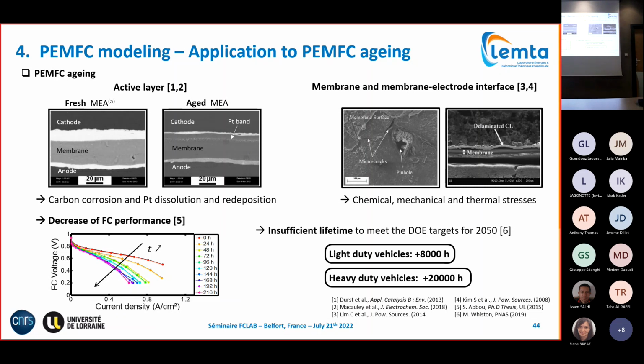Aging of fuel cell components primarily concerns the aging of your electrodes, more precisely cathodes, and to a lower extent the anodes, through carbon corrosion and platinum catalyst dissolution and redeposition, which will result in a lowering of the thickness of the cathode primarily and, to a lower extent, the anode. The impact on your operation is that you will have lower performance with time.